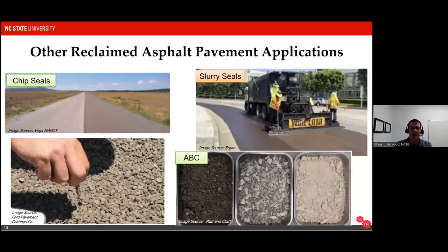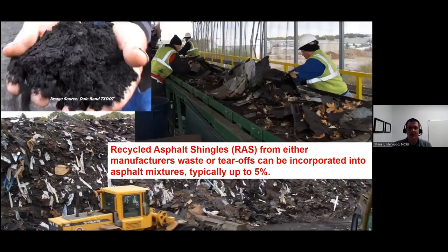A related material with RAP is recycled asphalt shingles. So these are shingles that are either removed from the roofs of someone's home during a roof replacement, or they may be reclaimed from a manufacturer's waste. So when manufacturers create the shingles, they may actually produce quite a bit of waste that can be incorporated and used in asphalt concrete. Technically, RAS are incorporated at up to about 5% dosage, much smaller than RAP, but the asphalt content for a typical shingle is much higher. So a typical reclaimed asphalt shingle might have something between 20 and 30% asphalt binder content. And so you use lower amounts of the shingles and get a total net benefit in the binder content.